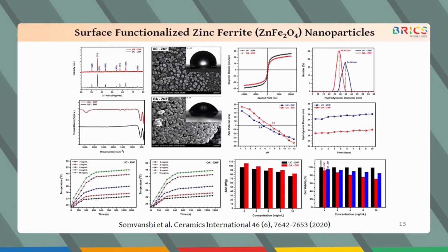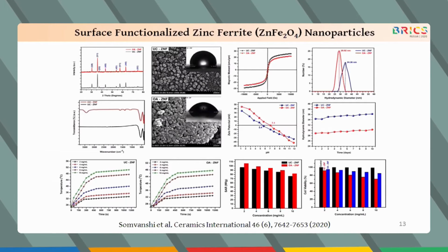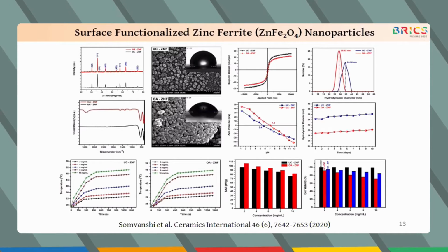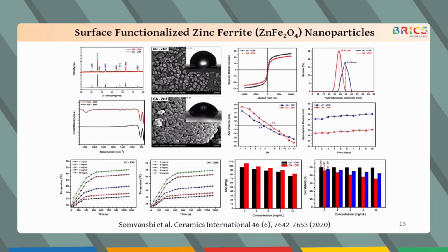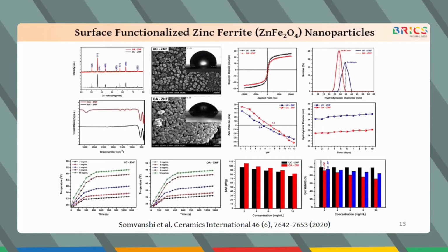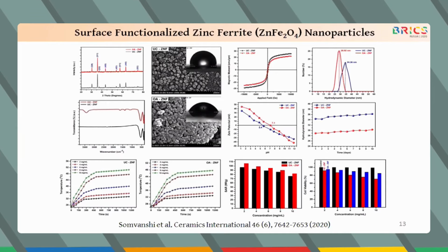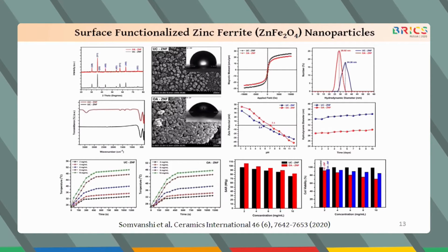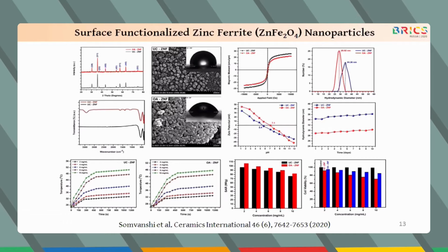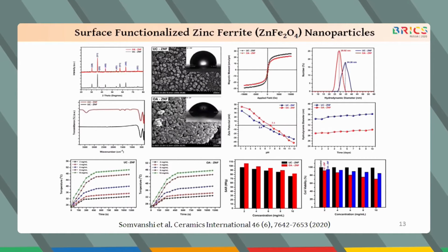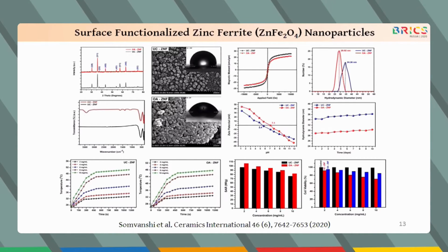The magnetic hyperthermia studies were carried out for different concentrations, that is for 2, 4, 6, 8, and 10 mg per ml of both the samples. The result shows that oleic acid coated zinc ferrite nanoparticles with a dose rate of 8 mg per ml are suitable for magnetic hyperthermia therapies for cancer treatment. The biocompatible nature of both the samples was studied by cell viability studies. It shows good biocompatibility as compared to other magnetic materials.